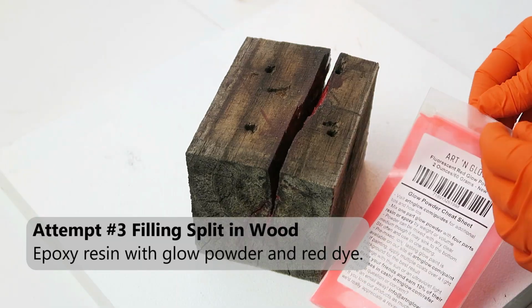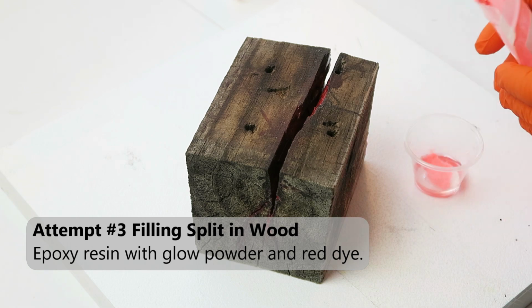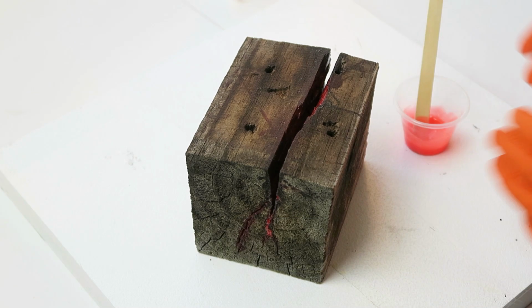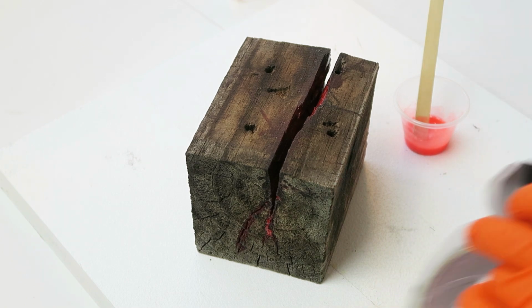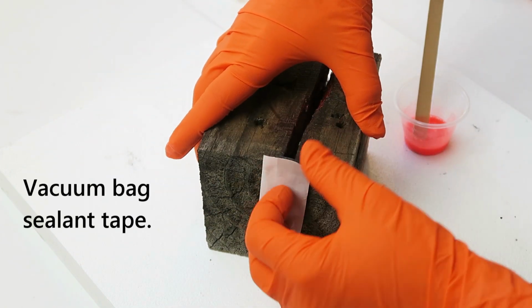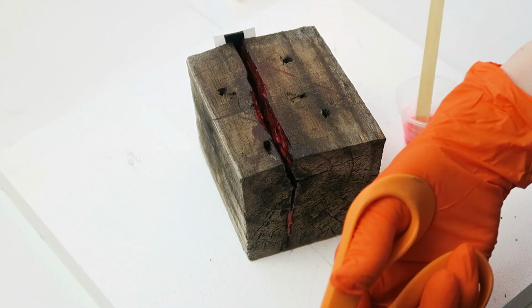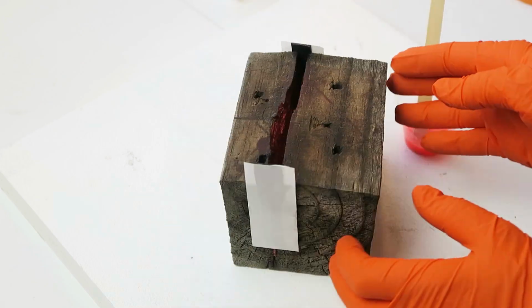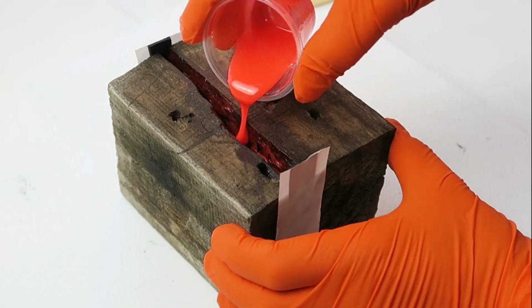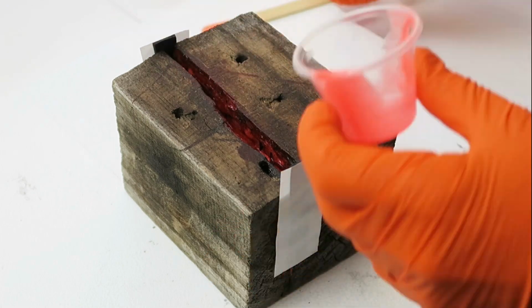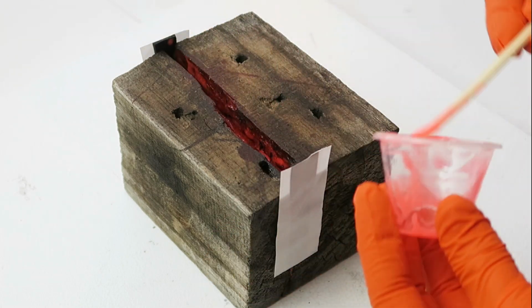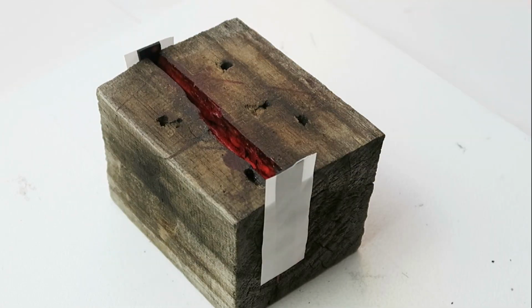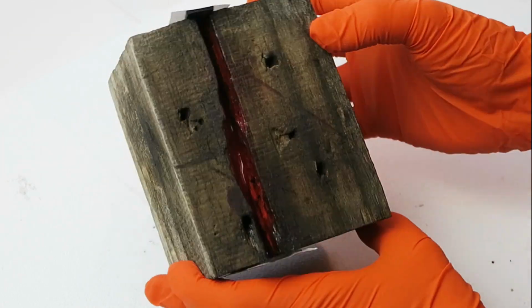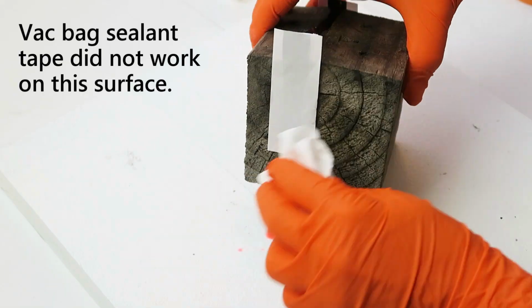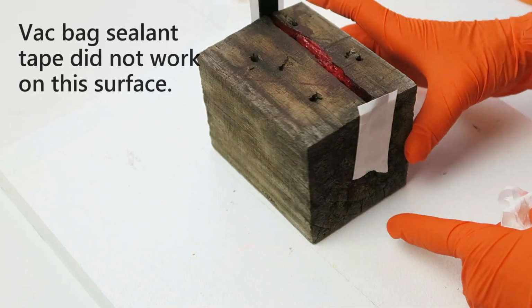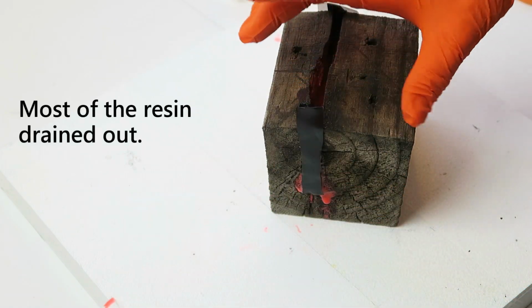For the third attempt at filling this crack, I stuck with just epoxy resin with dye and glow powder. To seal off the sides and keep the liquid epoxy inside the crack, I tried using gum tape meant for sealing vacuum bags. This leaked. The wood was too flaky and dusty to form a seal.